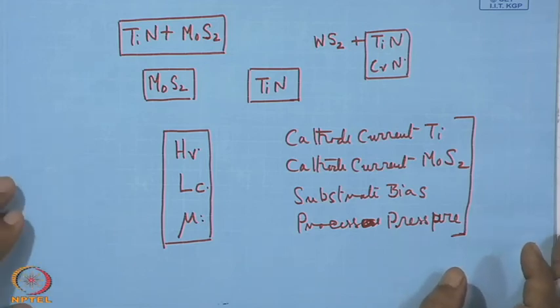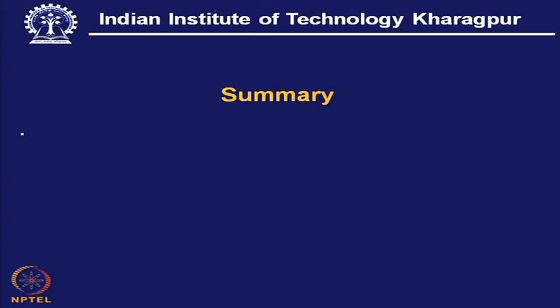So, with this we can make a summary of our today's discussion that MoS2 and tungsten disulfide, these are the materials which are called super lubricious material because of their architecture, and this hexagonal array of this one set of molybdenum that is in between two layers of sulfur. Now, molybdenum sulfur has a good bonding, but between the sulfur of adjacent layer the bond is weak, and that leads to a low value of friction because the van der Waals force of attraction is prevailing there.